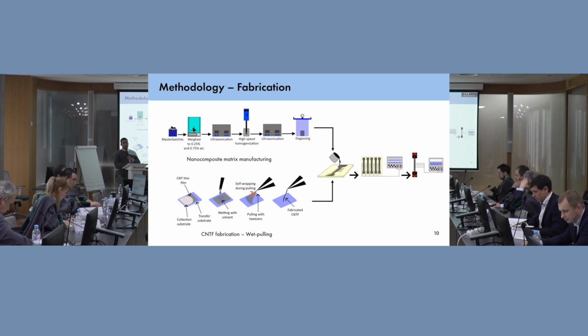Ultrasonication for another hour to help degas and disperse, a degassing step, and then to molding. But before we went to molding, we fabricated our carbon nanotube fibers using the wet pulling technique as shown on the screen. And then the rest is as the methodology described before.